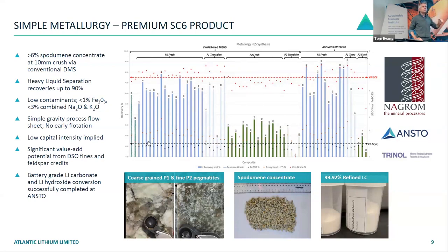The higher that iron is, it's a problem for the converters, because it actually starts to form a slag within the kilns. So every couple of weeks, they need to stop the kiln, scrape off all the slag on the inside of the kiln, and then start the plant up again. So they don't want to see iron in that concentrate at all. And the lower that is, the better your concentrate. So we're able to produce a high-grade spodumene SC6 concentrate.